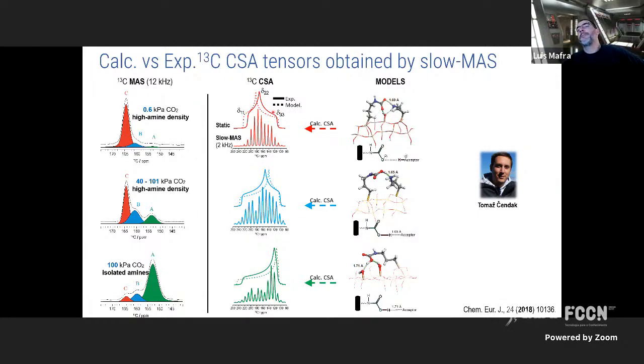The chemical shift anisotropy tensor is very sensitive to proton transfer. This is well known in the study of peptides and amino acids, okay? I took inspiration from these papers and transported that idea to these materials. As you can see, I start from our models and compute the principal components of the CSA tensor, and they are overlapped here in dashed lines. And this is the experimental one. As you see, the fit is not bad, okay?